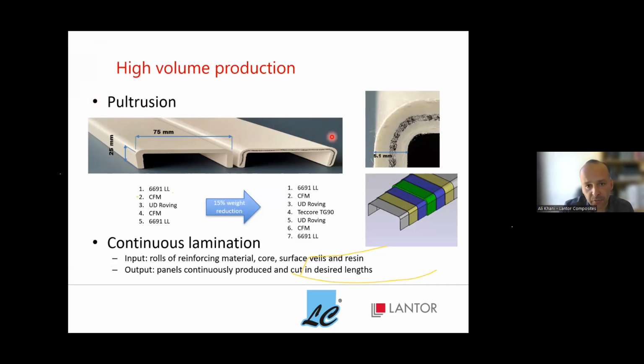For example, here we have done a trial. So we have converted this full glass laminate or profile to a profile with having the core in between. The black one that you can see here is a Teccore, it's a TG90. And basically here we were able to easily reduce about 15% weight just by substituting some glass fiber by the core.